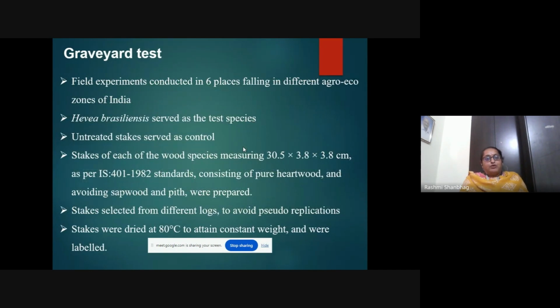The first test which was prescribed for wood preservation is called the graveyard test. As per BIS 4833, any wood preservative which will be used has to undergo this test and it has to prove good. Then only we can accept it. It is a field experiment. A lab experiment is also there as per the ASTM standard. But in case of India, it is only a field test which is recommended by the BIS. If it passes the field test, then only it can be accepted.